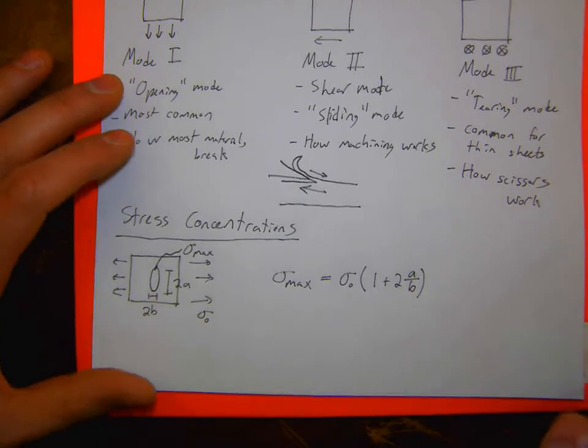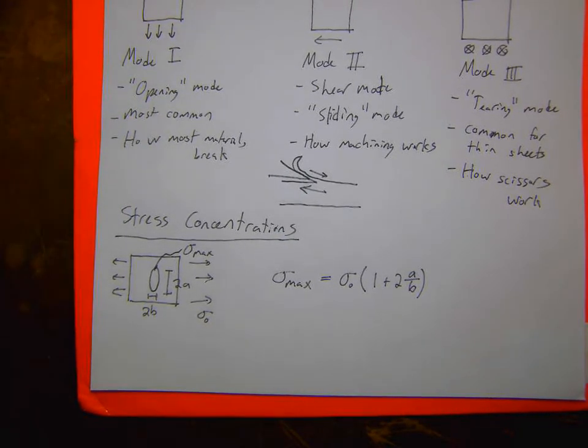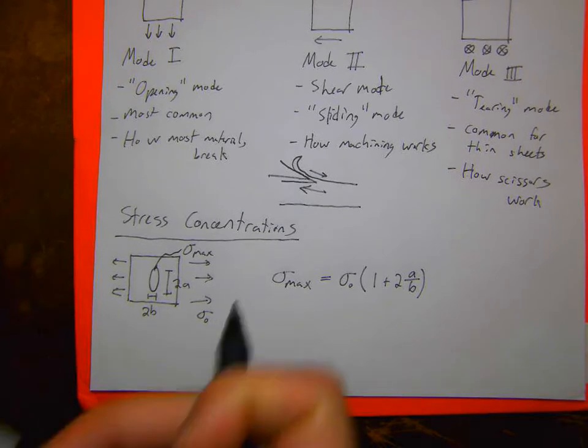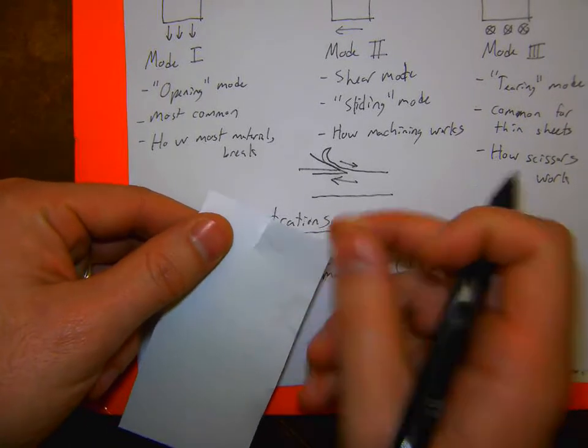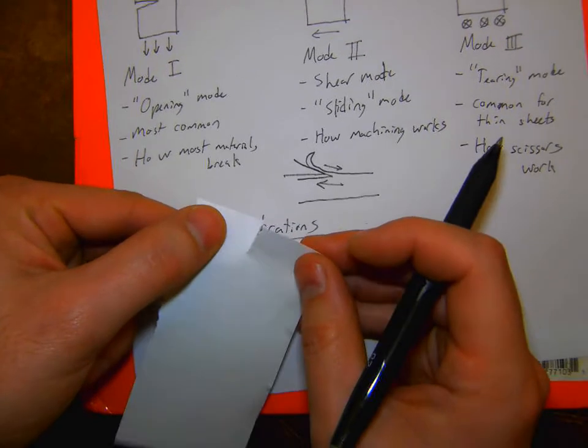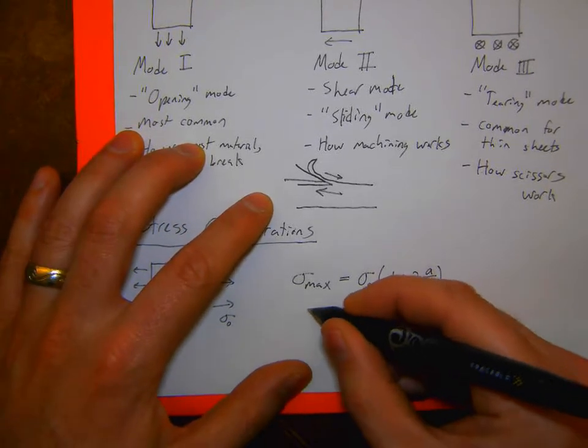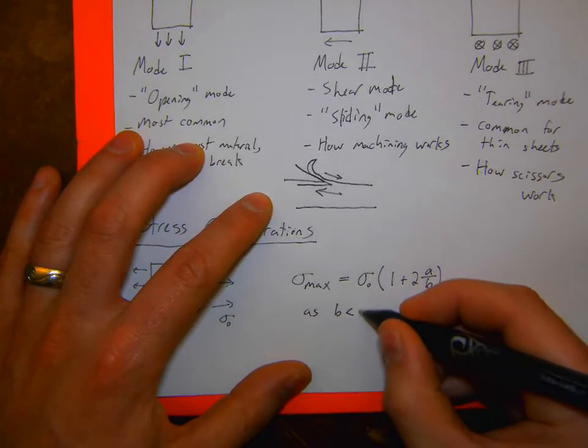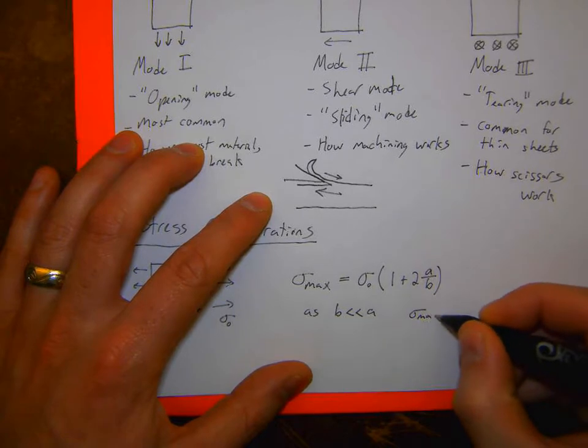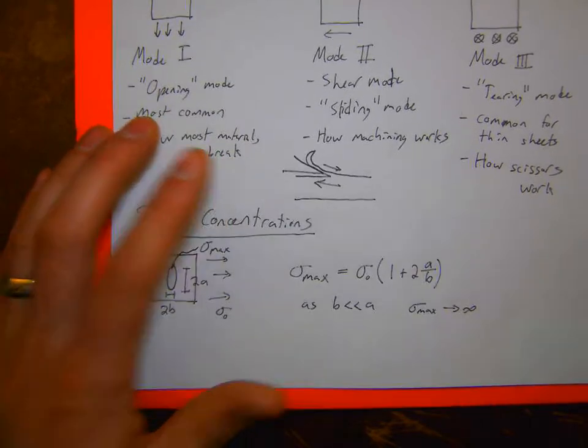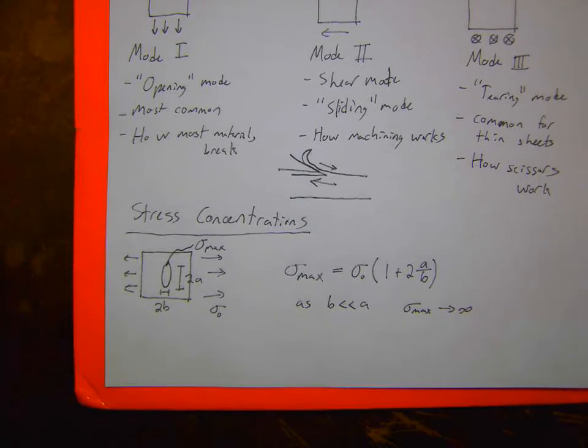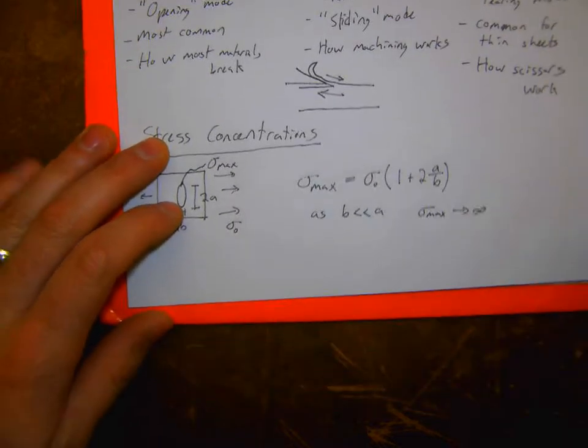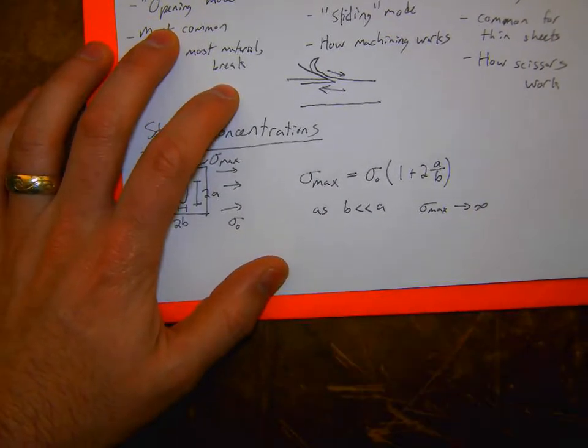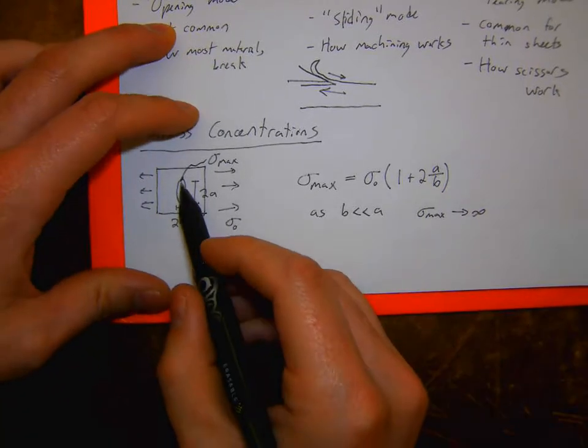There we go. But now what we want to be looking at is very sharp cracks. You can imagine for these sharp cracks, this is effectively a very high aspect ratio ellipse. I had also shown that as B is much less than A, then my sigma max would theoretically go to infinity, which isn't realistic because I just showed you a piece of paper with a crack in it, and it didn't just shatter upon applying a load.